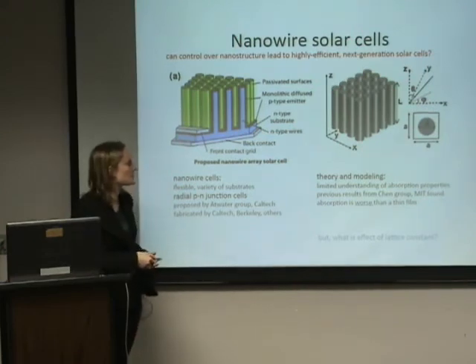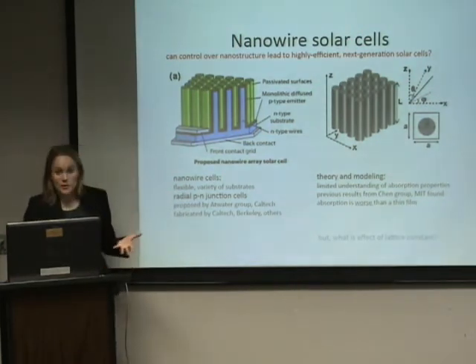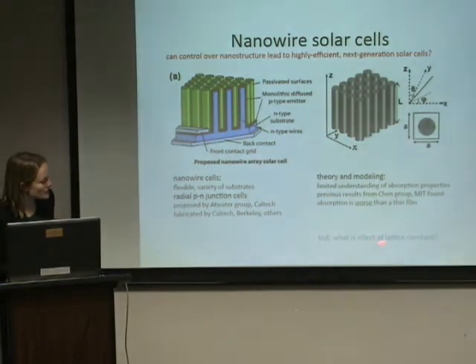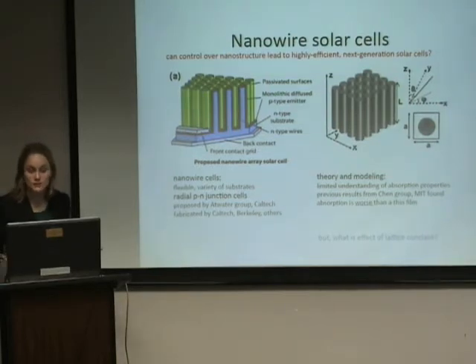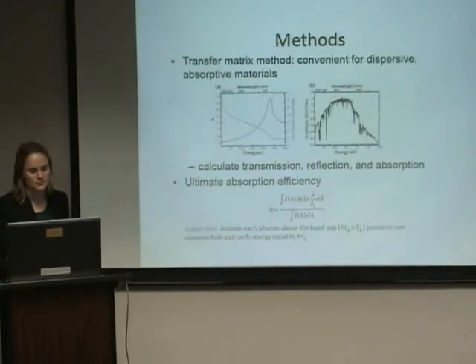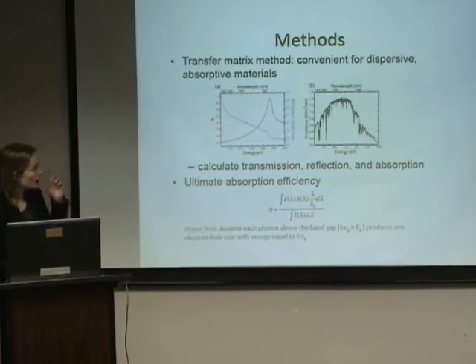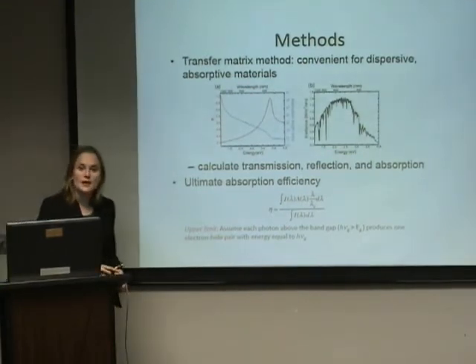Nanostructure doesn't help you. So we read that paper, and we thought that was pretty interesting, but we noticed actually that the one thing that they hadn't varied when they did their study was the lattice constant. In other words, lattice constant shown here, it's the separation between wires. And so my students started looking at what happens if you also vary this lattice constant parameter.